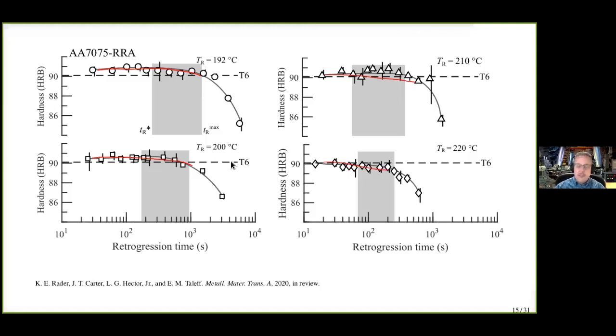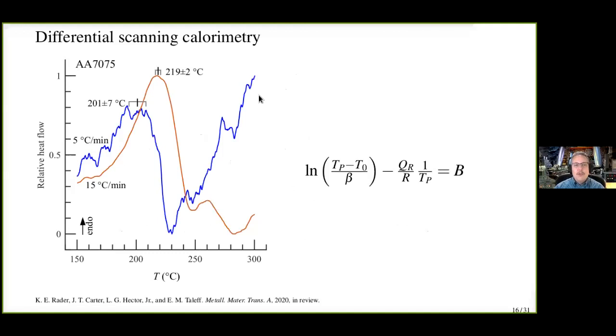Okay, so now on to the activation energy for retrogression. So reaging still works, as we talked about before. Well, to measure the activation energy for the retrogression, we turn to differential scanning calorimetry. Basically, what you do for differential scanning calorimetry is you take a small piece of material, in this case it was aluminum 7075 in the T6 condition. You put it into a device that will measure the heat input to raise the temperature.